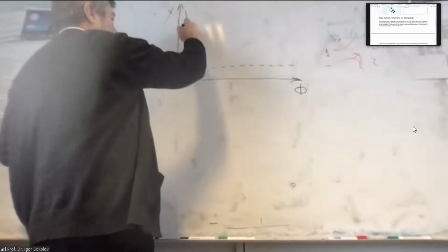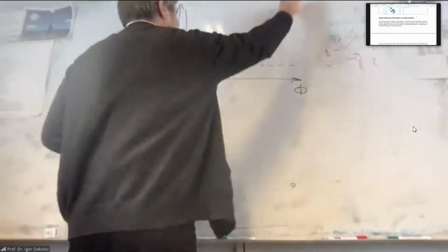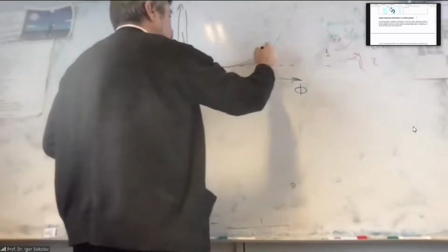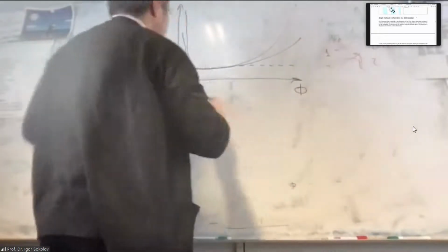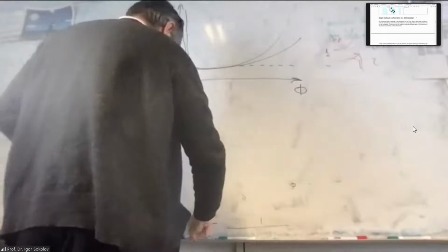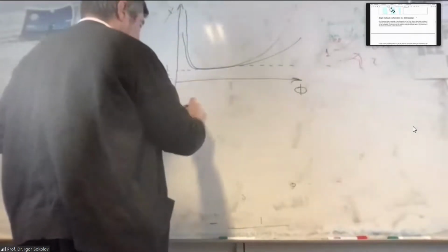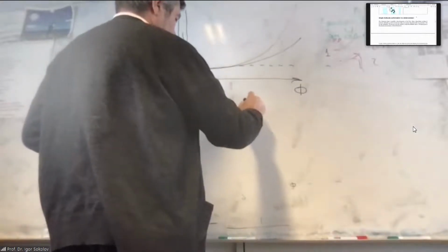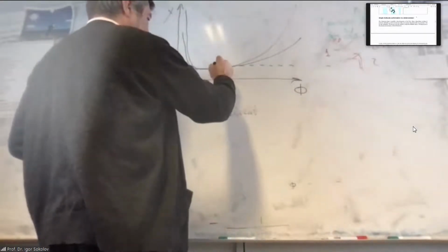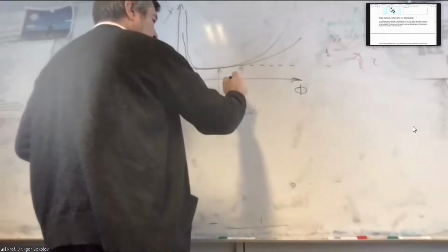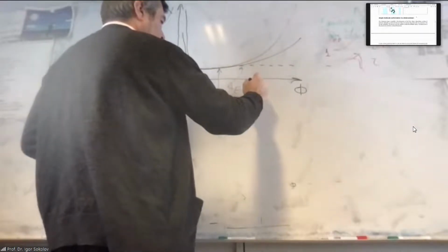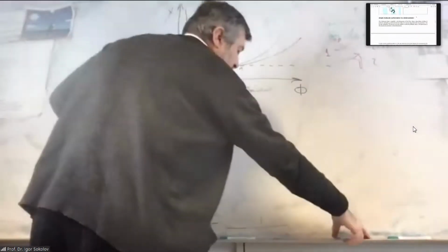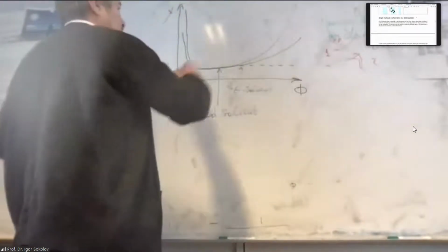And here was our spinodal, and here is our binodal. Here I have good solvent, up to this line. This line is called theta solvent. This is when chi is exactly 1/2. And here I have poor solvent.